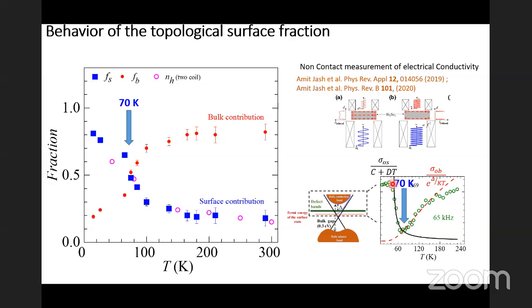Below 70 Kelvin, it is all topological surface dominated, which matches well with our measurements, which show a very high surface conducting fraction. But above 70 K, the thermally activated conductivity is coming from the selenium vacancies in the bulk. We believe that there is a band generated by the selenium vacancies about 70 Kelvin below the bottom of the bulk conduction band, and there are excitations across this which generate this thermally activated behavior.